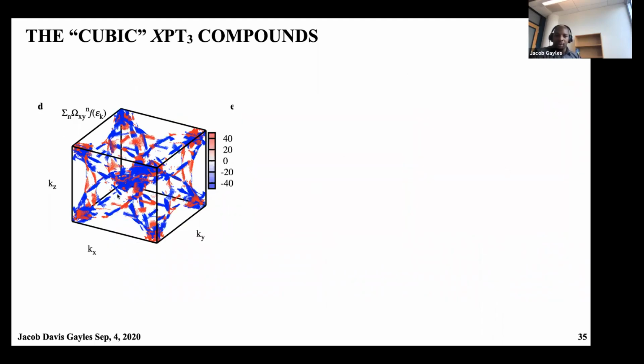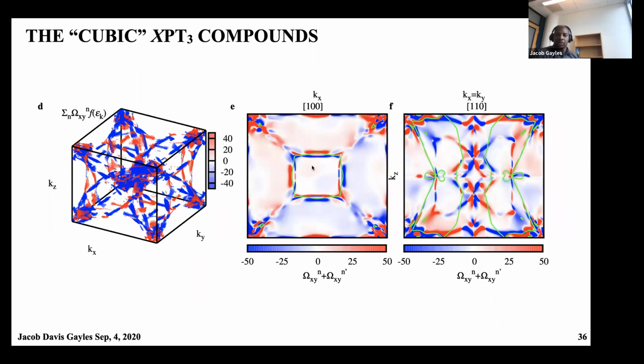Upon adding spin-orbit coupling, we generate this Berry curvature, which is shown here for the three-dimensional case. And these are the two planes shown here, where these degenerate nodal lines actually have a strong change in distribution from the non-SOC case to the SOC case, the spin-orbit case. And this is just the Berry curvature of those two sets of bands shown here. And this here is for all bands up to the Fermi energy.